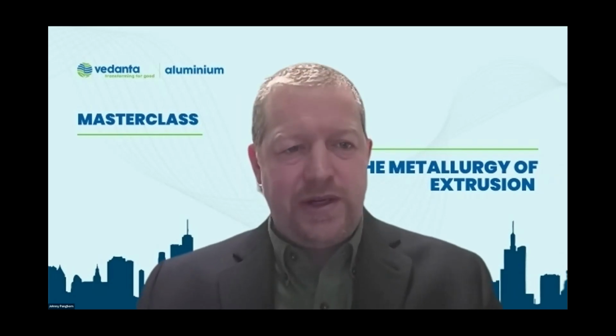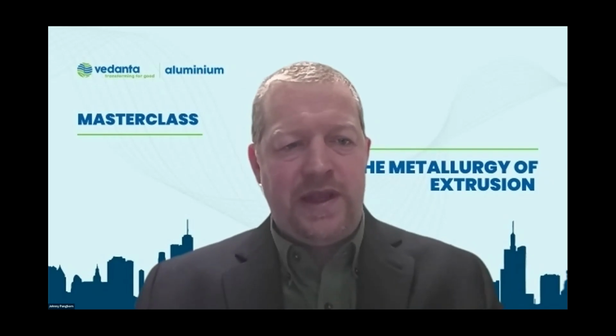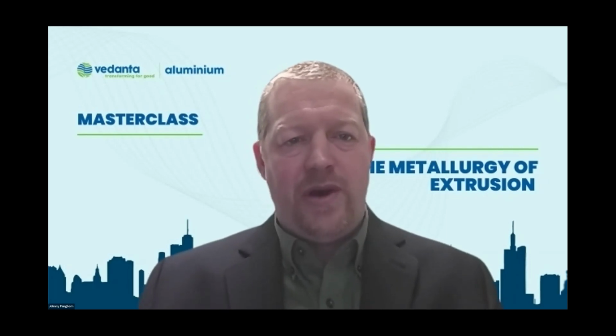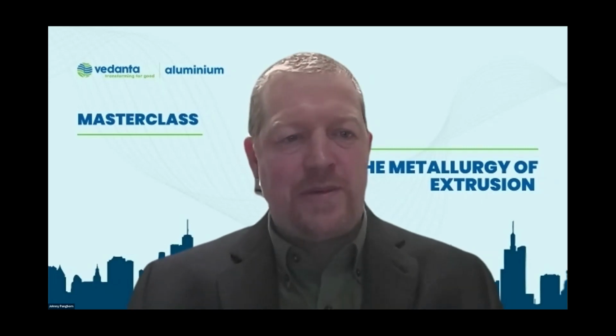So there's really a couple factors. One, the product has, I wouldn't say abnormal, but a less than optimum or non-optimum grain structure. And then two, the deformation. Usually you would see this after stretching in the process. After cooling, you're stretching and straightening. Although with a high pull force coming out of the press, potentially you can have that problem when it's still hot, before the cooling process.